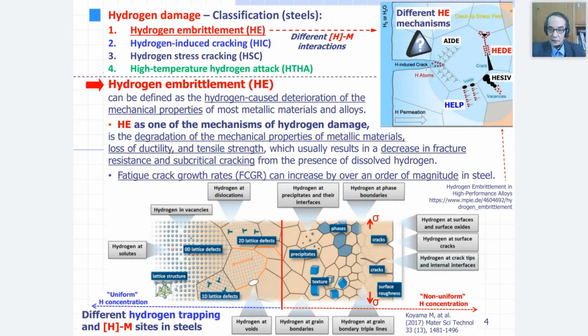We need to make a classification of hydrogen damages. As you can see, in the case of steel, we could divide into 4 groups. The first one is hydrogen embrittlement. The second is hydrogen-induced cracking, which is not the same mechanism as hydrogen embrittlement. The third one is hydrogen stress cracking, and high-temperature hydrogen attack. Due to different hydrogen materials interaction, as you can see in the upper right part of the slide, different hydrogen embrittlement mechanisms with acronyms AIDE, HEDE, HESIV, and HELP could appear, very complex mechanisms on a nano level.